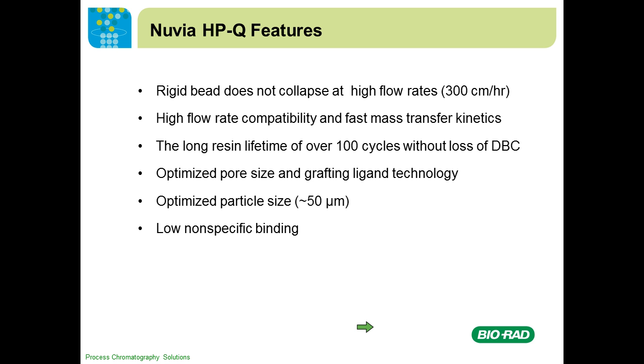And the resin is quite stable. We will later show you the cycling study, which shows there is almost no loss in dynamic binding capacity during the 100 cycle study. Since, as I mentioned, we have already optimized the pore size and the grafted ligand technology, we are able to improve the binding capacity and mass transfer kinetics. And meanwhile, because the bead is rigid, we are able to make it a 50 micron bead, and that helps fast mass transfer of the large biomolecule into the bead.